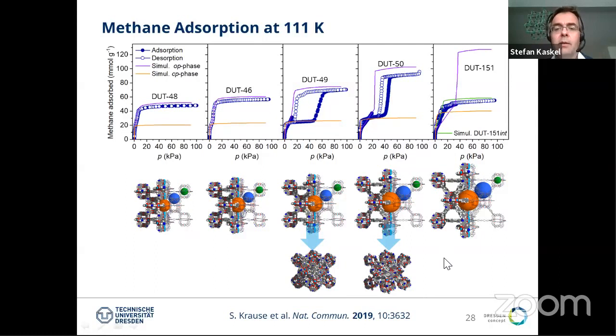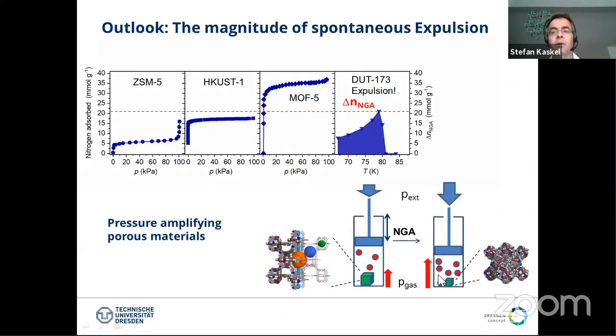But from this, we can predict and we can deduce new criteria. And so there is a critical length needed basically to be able to buckle to compensate the energetic transformation, the delta F, and also there's a critical volume difference needed between these two forms in order to achieve the NGA. So with this, I conclude my presentation on the counterintuitive behavior.